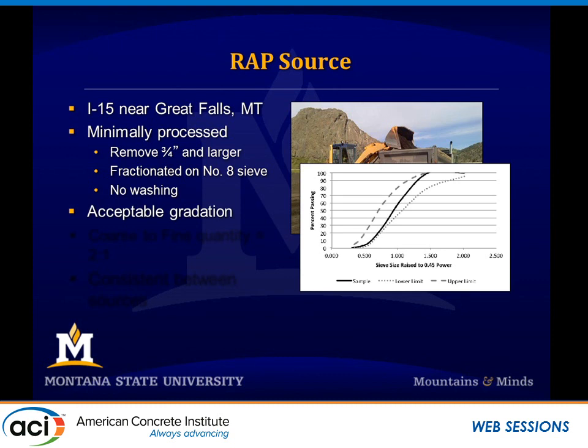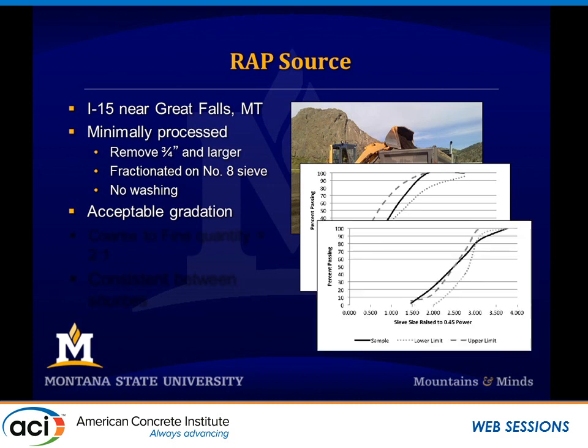This process yielded acceptable gradations. So this is the gradation curve of the fine aggregates. And you can see it's within the limits of the MDT specifications, or you just take my word for it. That's within the MDT specifications for fine concrete aggregate. In terms of the coarse aggregate, we deemed this acceptable. It's off on a couple of sizes, but not too bad, especially considering where we got it, right? Just milled it up off the surface, split it on number 8, and called it good, right? And so that was our minimal processing that we did.